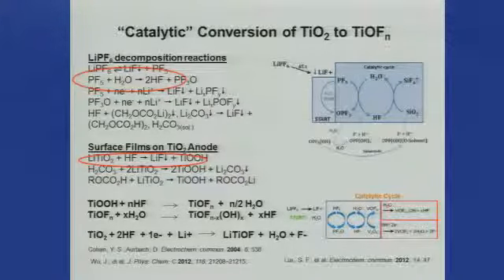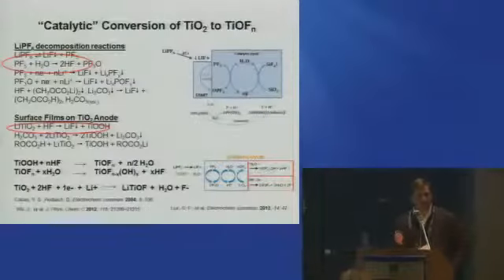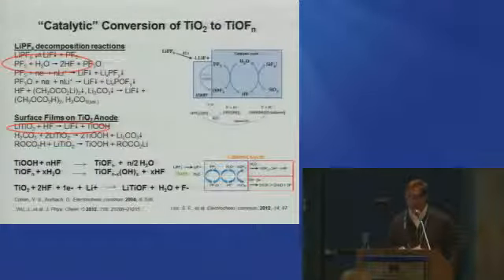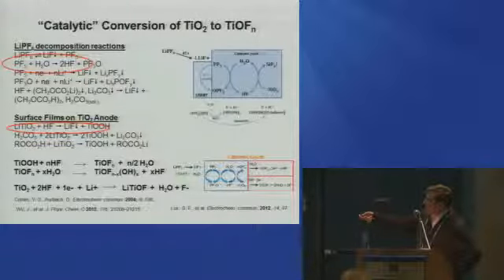And so some of this surface chemistry is really controlled by when you make materials, especially titania. If you have surface hydroxyls, those can be reactive, especially in the presence of lithium salts. What's even worse is if you have the hexafluorophosphate anion, it's not as thermally stable, and in particular, that can actually decompose to form PF5, which then reacts with water to form HF. This is a gaseous species, so then it evolves out of the cell.